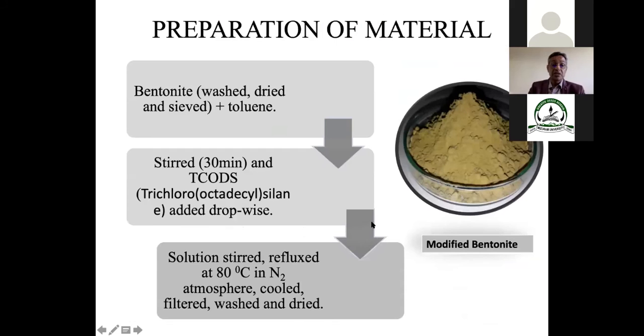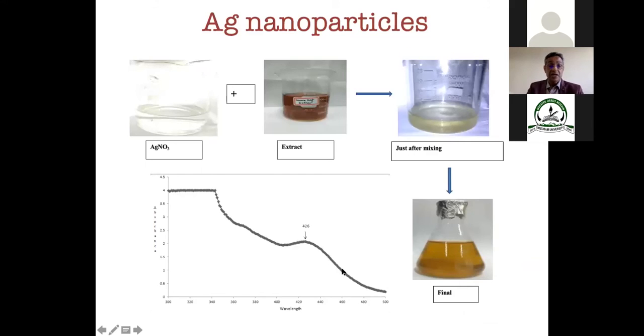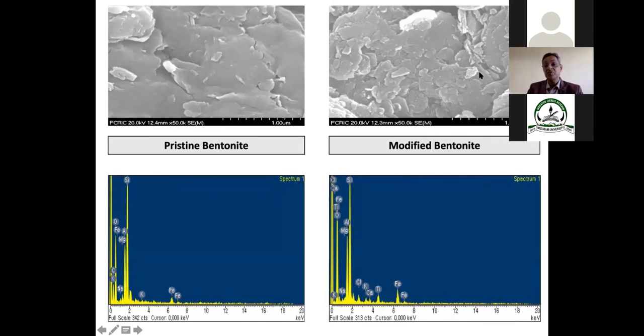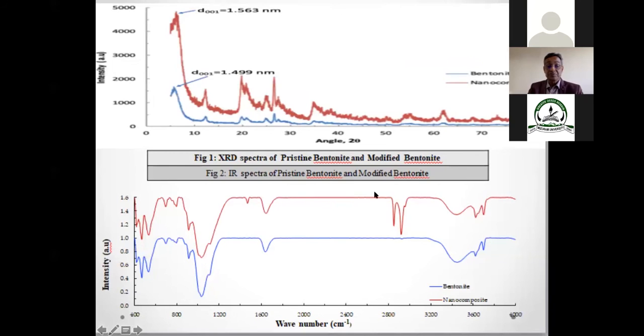This is the material which I have shown here, the modified bentonite with TCODS, trichlorooctadecyl silane. With this material we obtained the same kind of images. You can see that the organic molecules are clearly visible here, and this is the EDX data we obtained. With that we tried to confirm, and then the IR data also. Here you can see that the additional peaks are coming, which confirms that the organic molecule has been introduced. What is the d value for the 001?